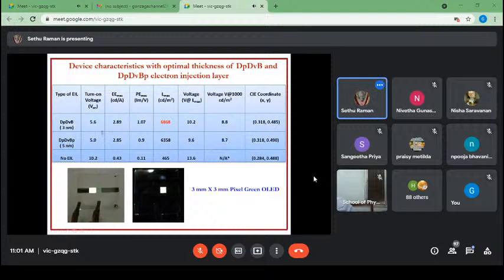So we carried out organic light emitting diode fabrication using organic small molecules. All are organic small molecules prepared under high vacuum condition using a thermal evaporation technique. This is a 3 mm by 3 mm pixel green OLED. By using this electron injection layer, we have achieved very good luminescence properties, more than 5 times enhancement, and we have also reduced the turn on voltage from 10 to 5 volt. It was a good work; I carried it out almost 12 years ago. This is a small organic small molecule based work, and this is the summary of that work.